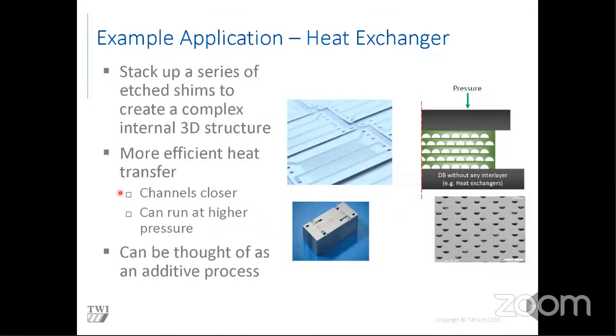So you can see the small distance the thermal heat has to transfer before it goes into the cold fluid. Because the channels are closer, they're more efficient, but because of the diffusion bonded joints, which I previously showed, which are almost invisible, the strength you can get from them can approach parent material. So you can actually run these at higher pressure as well to increase your efficiency. Because of the way we can use diffusion bonding and these shims, I like to think this is an additive process because you're adding several building blocks together to create a final part. And you can express yourself quite a lot in the design of these shims. So I think of it as an additive process. Not a traditional additive process, but a quasi additive process.